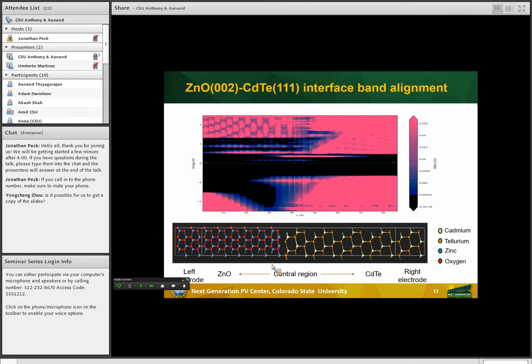It was also challenging to find an appropriate Hubbard-U parameter to match band gaps, but reasonable values of band gaps and band offsets were obtained using the GGA half technique. The interface appears to be pretty clean and free of electron states, although there seem to be some states. This plot also bolsters the theory. Zinc oxide does not create a significant band offset, right? Although there is some band bending in the valence band, which may not be beneficial.